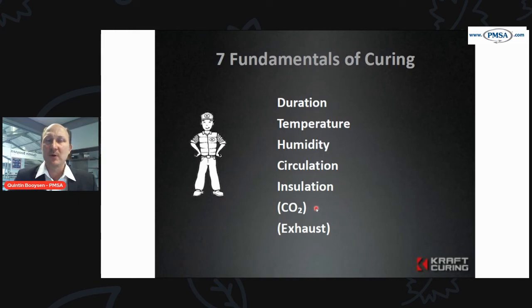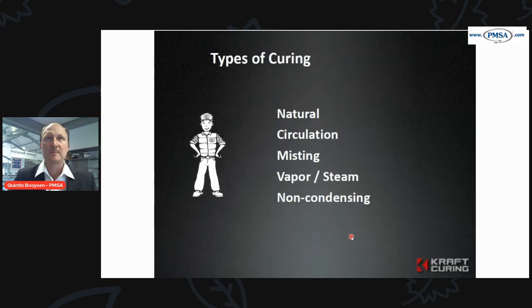And CO2: we spoke earlier about the calcium hydroxide, which meets with the carbon dioxide to form calcium carbonate. So if we can have carbon dioxide in our system, that's a big plus. Exhausting: we spoke earlier, if you exhaust, you can allow that free moisture that's in the system to get out. You can be in better control. So that's exhausting your controlled environment. So that's also a critical part of curing.